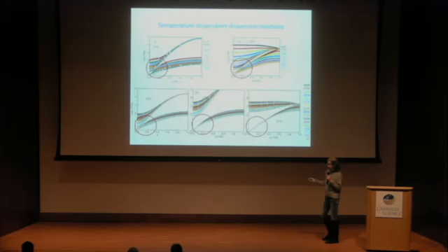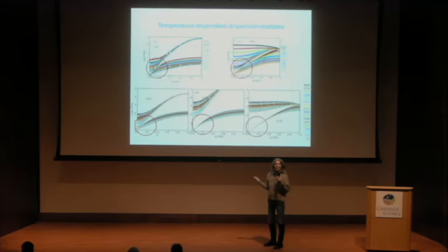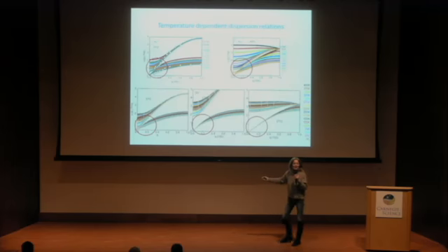Now I draw these red circles into the dispersion because I wanted to attract your attention to the fact that optic and acoustic mode are interacting with each other at low Q values. So you see here directly, if you look at the open squares, that this mode gets affected by the optic mode. This means you get a softening at finite Q, which tells you that you have a softening on the dimension of a couple of lattice constants. So this could give rise to polar nanodomain formation or elastic anomalies.